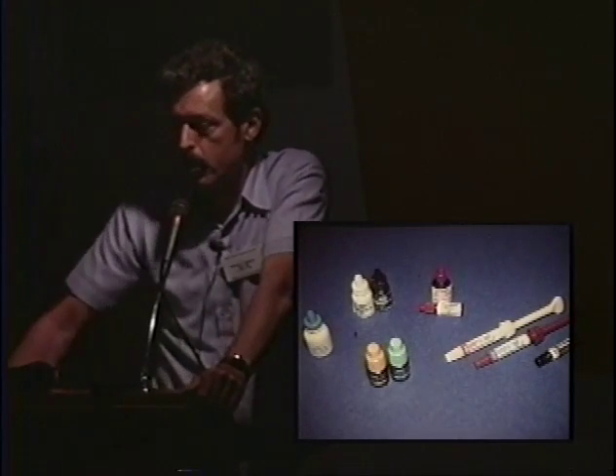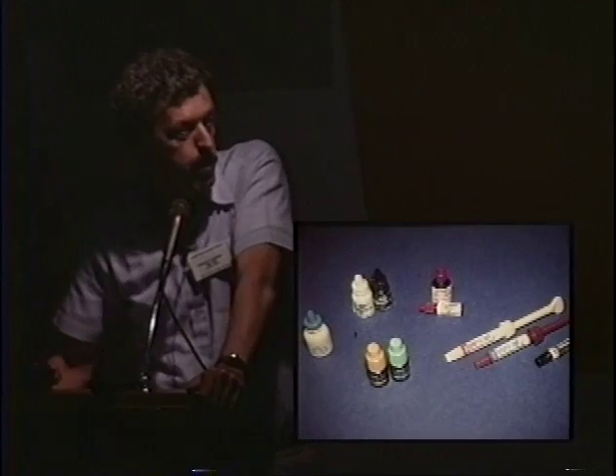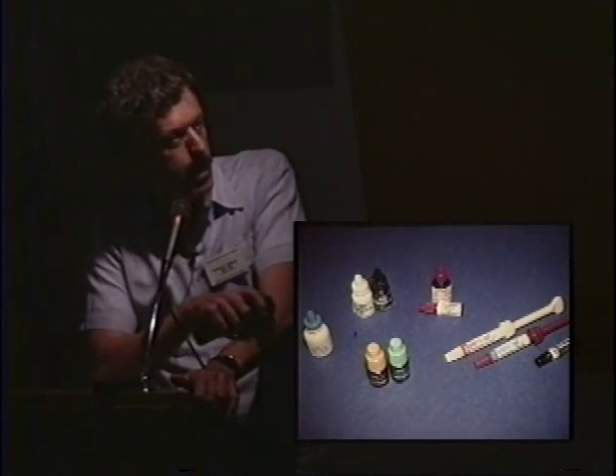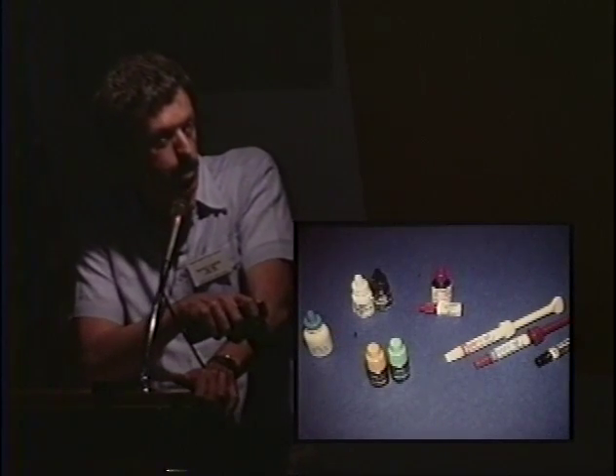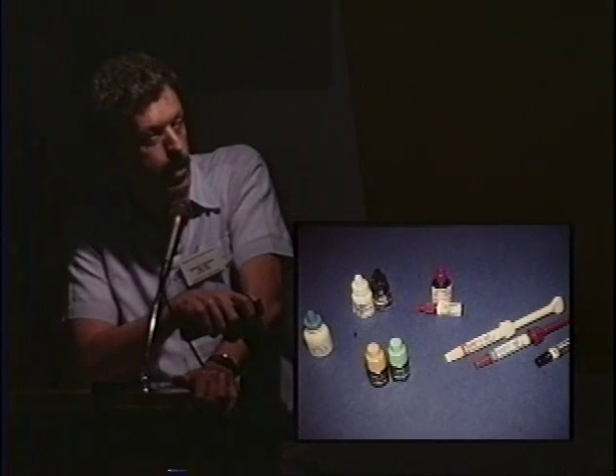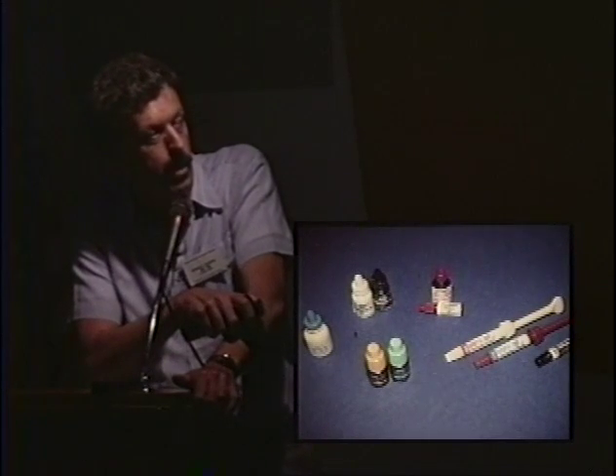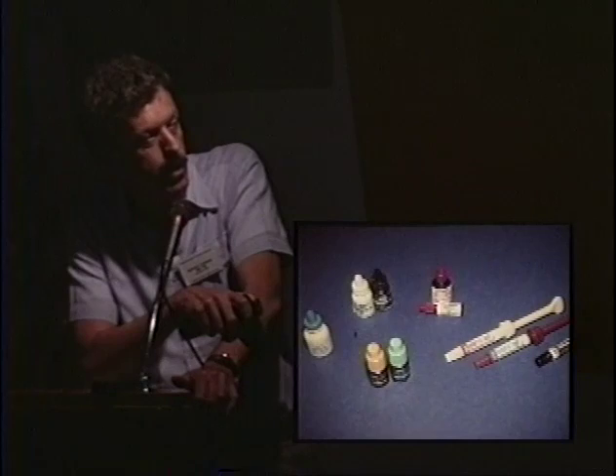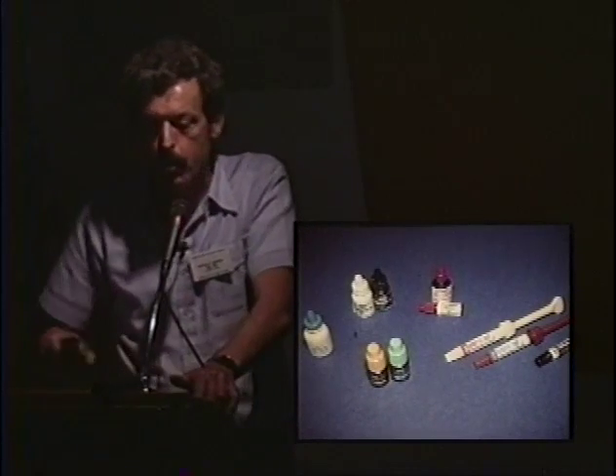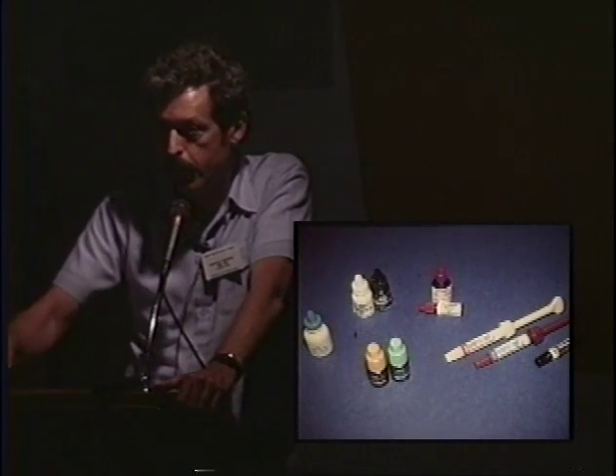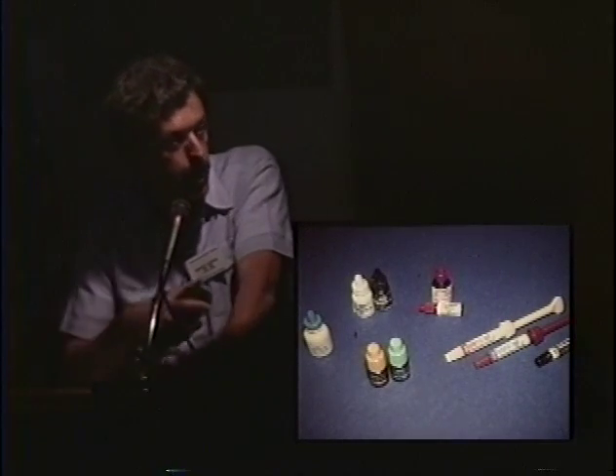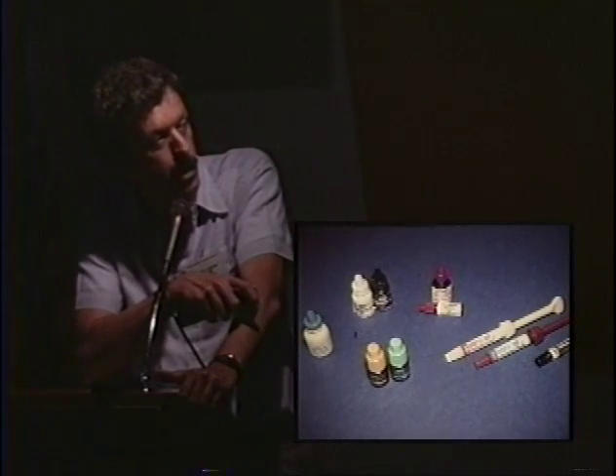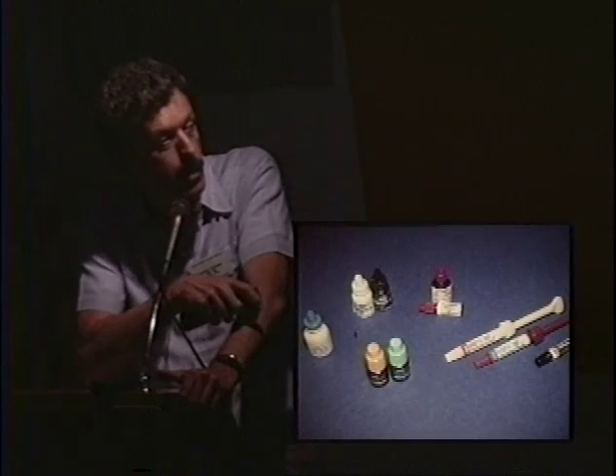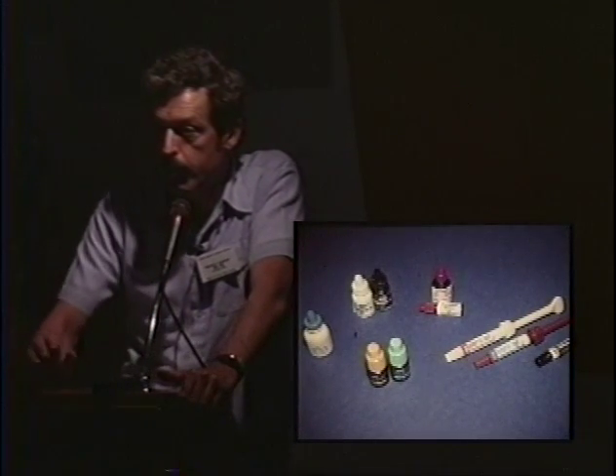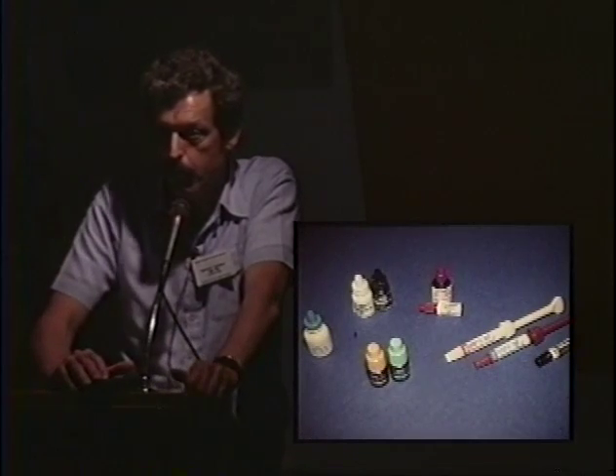Okay. Yes? Do you light cure the AB under composites or just under? Well, in the case of All-Bond, they say now that you should light cure this if you're not going to get light to it, say, for example, through this layer. So if you're putting this layer over it and you're light curing this layer, that light will transmit into the AB, and there's no necessity of a separate step of light cure. But let's say that you were going to bond a crown, for example, the primer AB, an opaque crown, maybe a gold crown, then you would want to light cure AB because you're not going to get light to it in the future. Okay, that would be a clinical improvement.